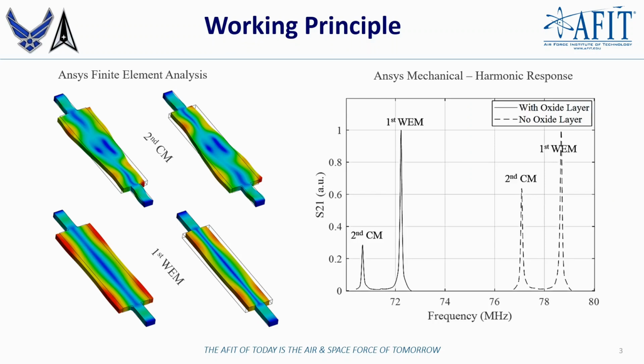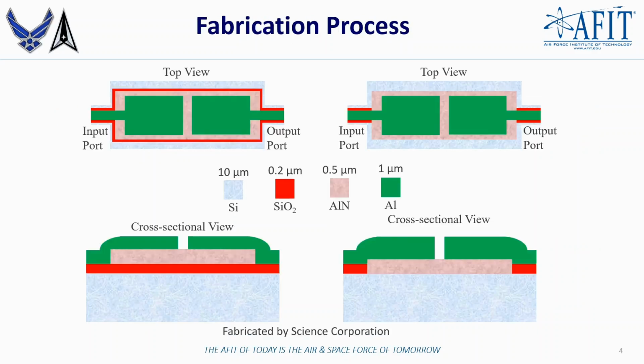On the left here, we have finite element analysis simulation of two adjacent mechanical modes that we call second contour mode and the fundamental width extensional mode. These modes are transduced by 500 nanometer aluminum nitride layer deposited on 10 micron thick silicon layer. We fabricated two sets of resonators, with and without oxide film, as you can see in here.